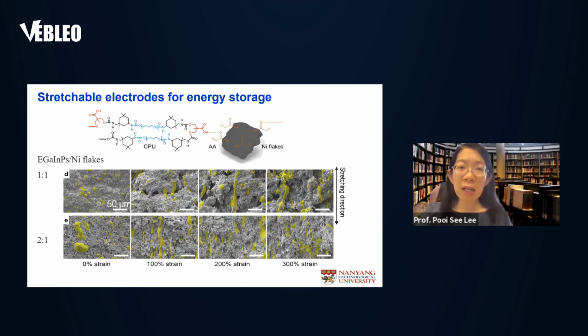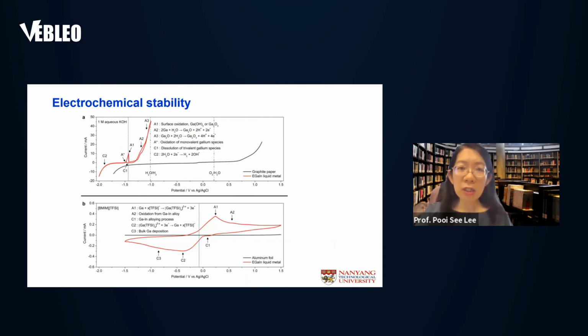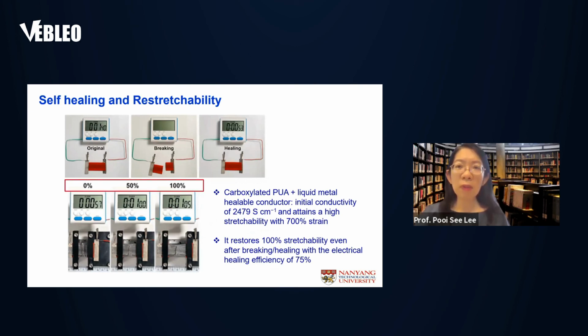So as shown here, there is the hydroxyl group that's interacting with the fatty acids on the surface of the nickel flakes. And this leads to a good physical anchoring and chemical interaction at high strain for energy storage applications. With the addition of liquid metal, we also study the electrochemical stability, both in the aqueous electrolyte in figure A and the ionic liquid in figure B. As we can see here, the liquid metal is not very stable in aqueous electrolyte. Whereas in the ionic liquid environment, it creates a highly stable electrochemical performance, which makes it interesting for a highly stretchable electrochemical energy storage that is also healable.